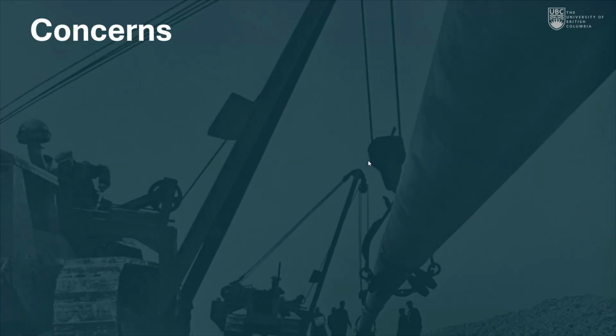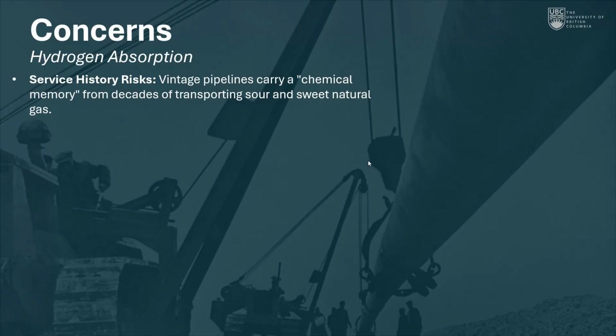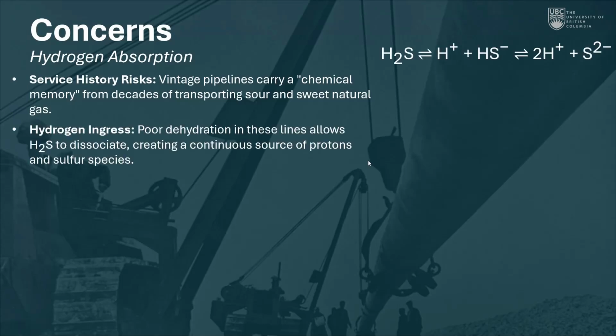And today I also want to focus on a concern of hydrogen absorption, leading to hydrogen embrittlement, cracking, or blistering issues. So when we're looking at repurposing vintage assets, we are also interested in the cumulative history. So what has accumulated over the lifetime of that pipe. And typically a lot of these lines were serviced for sour and sweet natural gas transport. What those two words refer to is the concentration level of hydrogen sulfide.